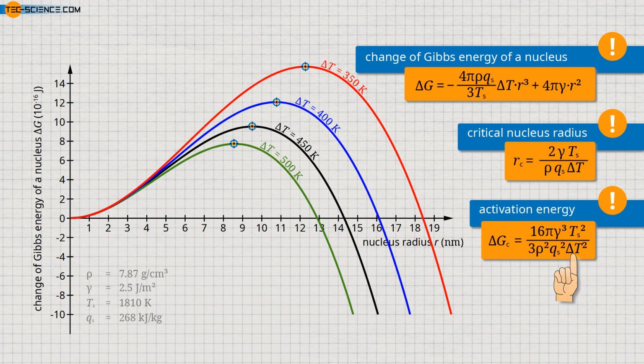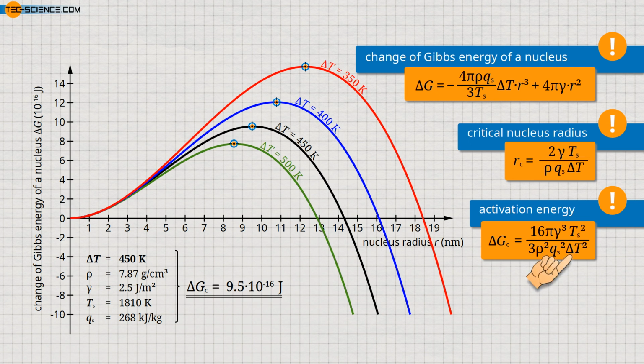For the example given earlier, this results in an activation energy in the order of about 9.5 times 10 to the power of minus 16 joules. It should be noted that both the activation energy and the critical nucleation radius increase with decreasing supercooling and become infinitely large when the solidification point is reached. Stable nucleation is therefore not possible at the solidification point.